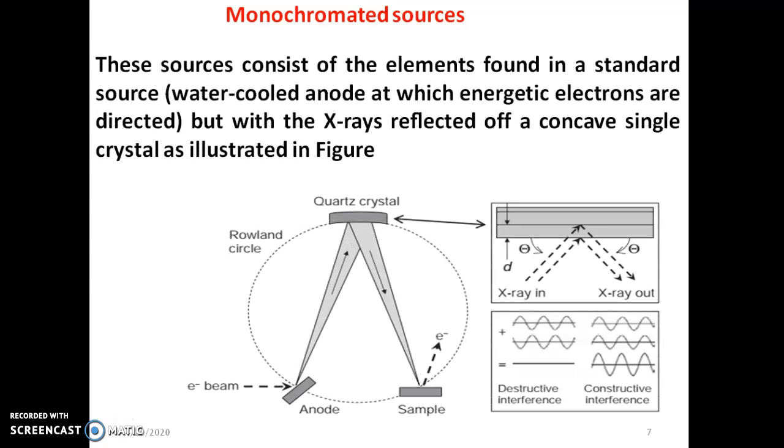In the case of charged particles, collimation and modulation can easily take place by using magnetic and electric fields, but X-rays are neutral rays. Therefore, the application of magnetic and electric fields for collimation or modulation does not work. So there is a need for another concept. In the case of X-rays or neutral particles, the diffraction phenomenon is used for collimating and focusing the radiation. Now, this diffraction phenomenon is used like this.